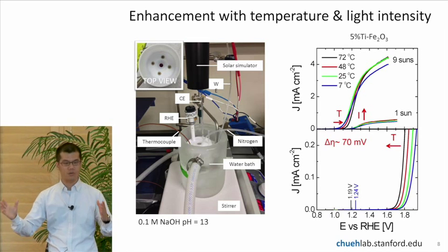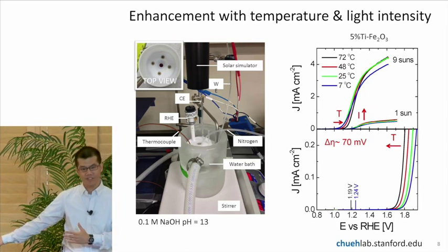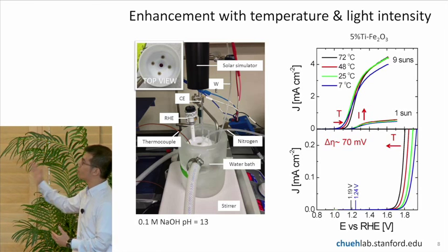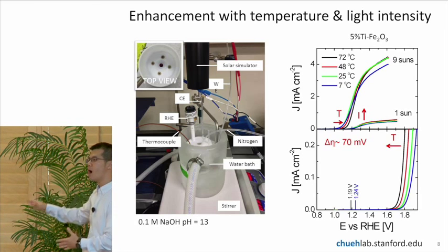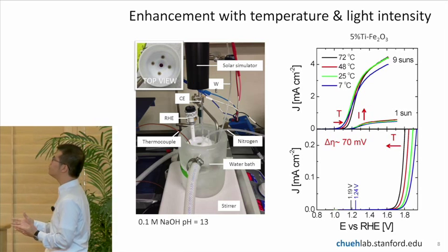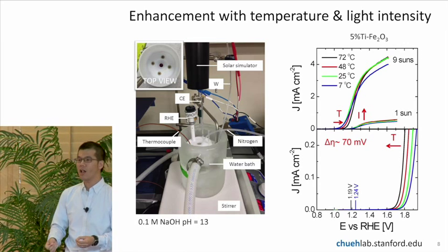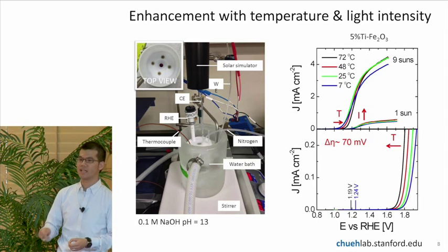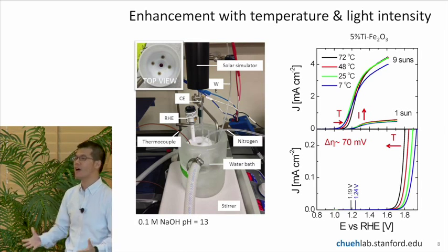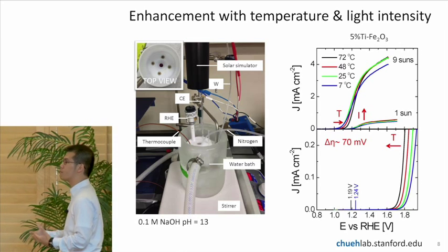But the actual voltage decrease we see, the shifting to the left of the plot, is actually much more significant. So from the bottom plot, we can conclude that by increasing the temperature, we're putting thermal energy into the electrons and the molecules to improve the rate of electrocatalysis. So even without light, iron oxide is functioning as a better material.